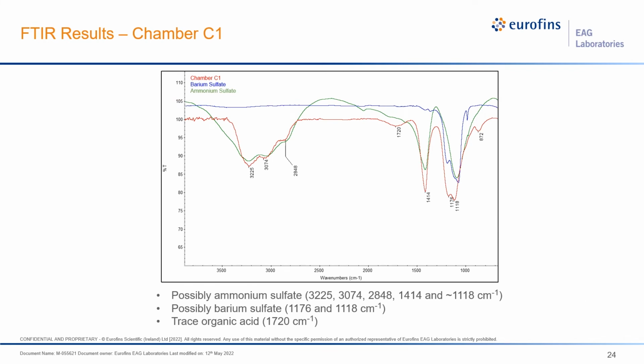Now with the third lab, this is our third one. This one actually did appear to be quite a bit more contaminated. Here we have a couple of things that we see. First of all, we see ammonium, and this is actually a pretty strong signal for some kind of ammonium salt, especially with these particular peaks and the 1414. The other thing we see is possibly some kind of sulfate compound.